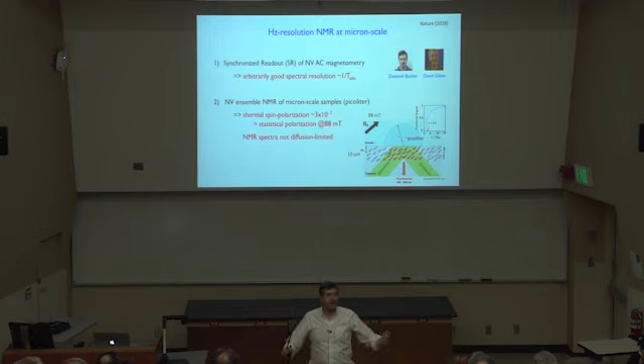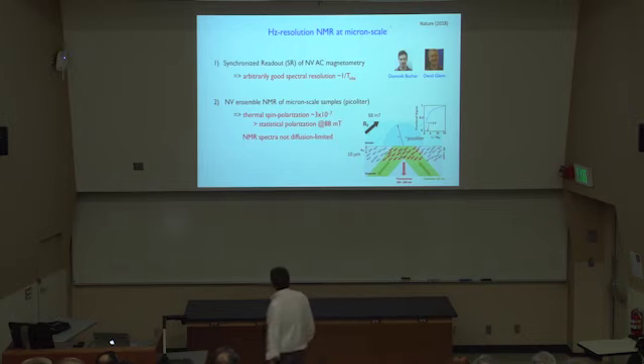If you have 10 to the 10 spins, 1 over square root of n might be 10 to the minus 5. If 10 to the 16 spins, 1 over square root of n is about 10 to the minus 8, which is what we have there. So get a bigger sample, and statistical polarization fluctuations go away. Diffusion, that's still going on, yep. But it takes a lot longer to diffuse over a micron scale than a nanoscale, and that can become sufficiently long that that's not a problem either, right?